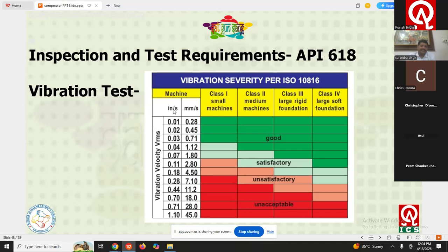On the left side you can see this is inch per second. So this is a conversion. If you are measuring in inch per second, that is 0.01. So this is basically the acceptance range for class 1 for my compressor. For class 4, my acceptance range is up to 2.8.